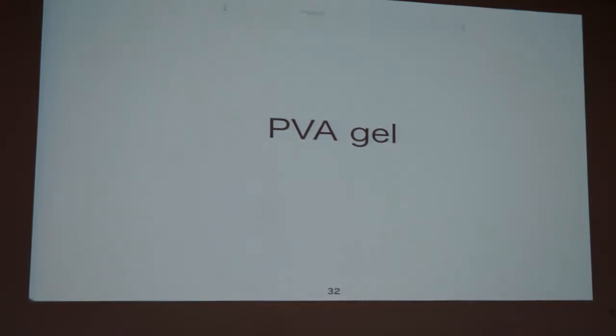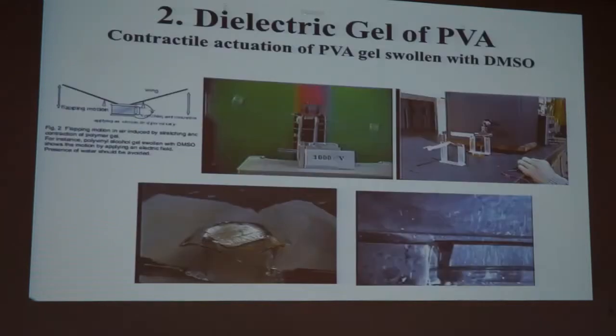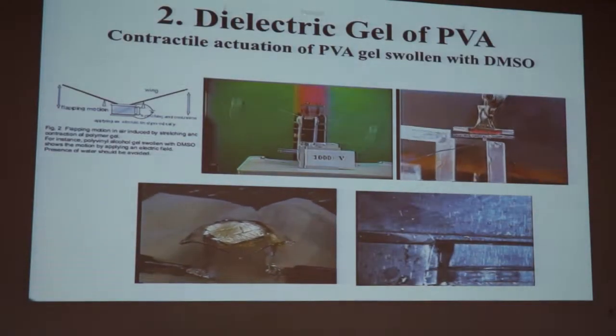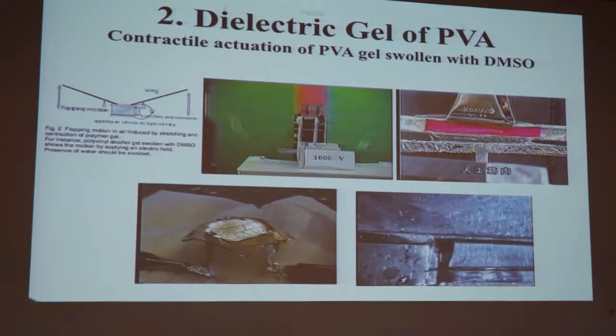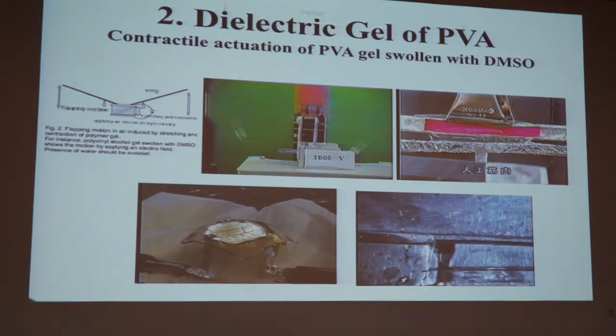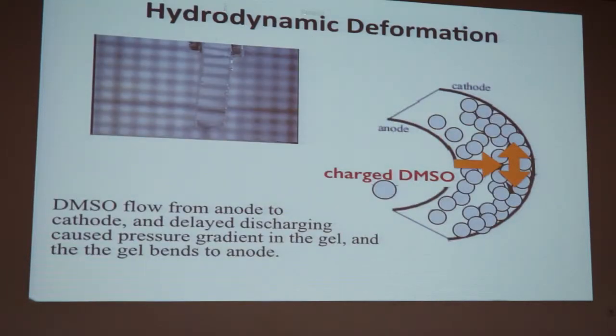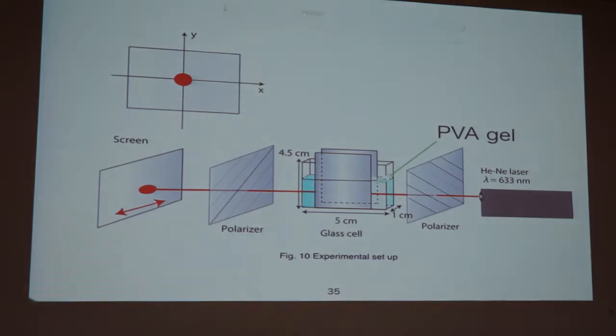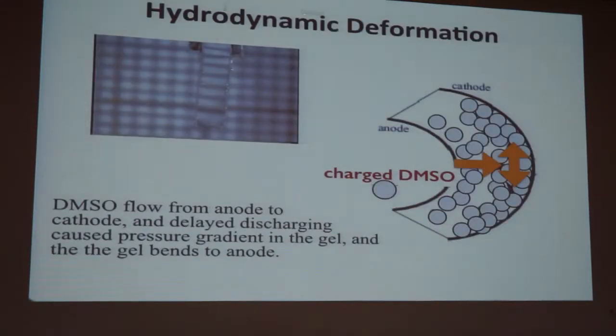It can be used. It shows very efficient deformation. But from the viewpoint of electro-optical function, it might have something. This is the PVA gel. A long time ago, we carried out this kind of experiment. It deforms very efficiently. This is another example. Very strong deformation can be obtained. Within 40 milliseconds, 90 degree bending can be achieved. This thickness is, I think, very thin, but it works very efficiently.